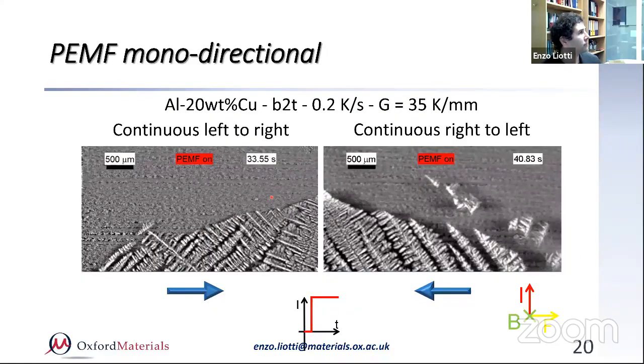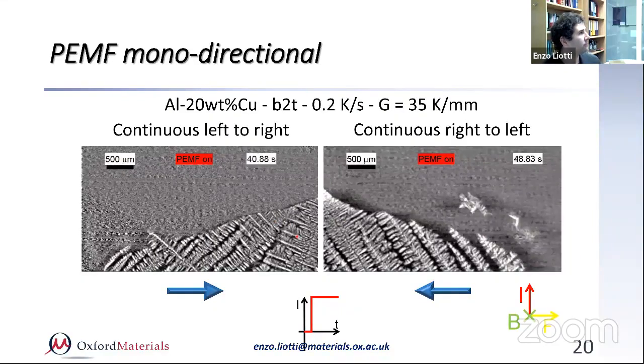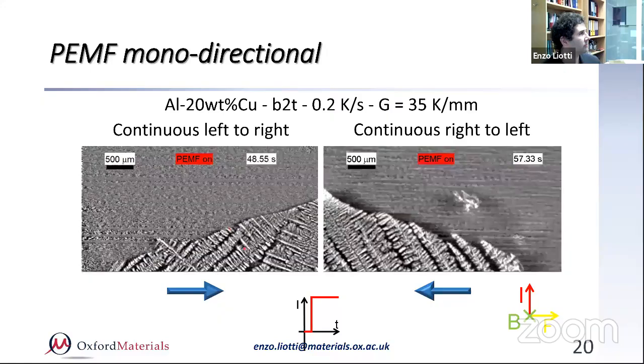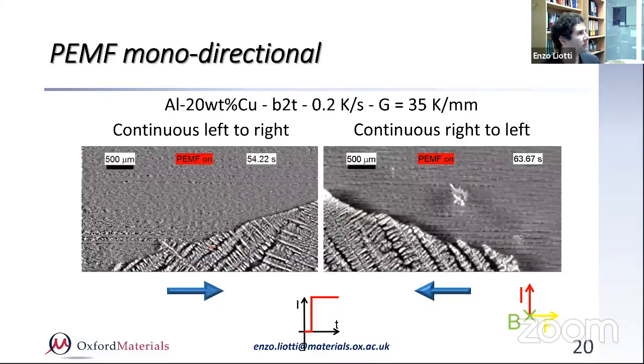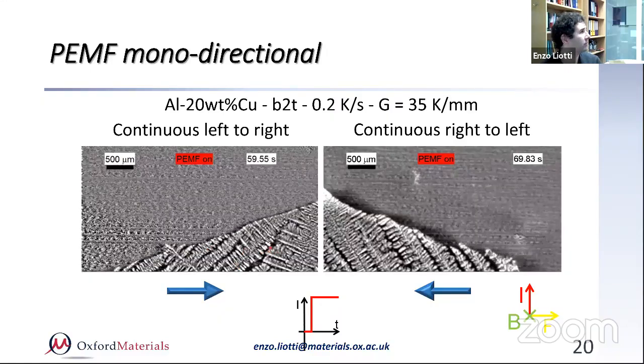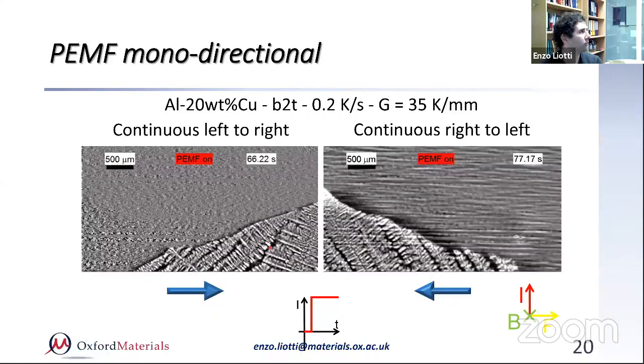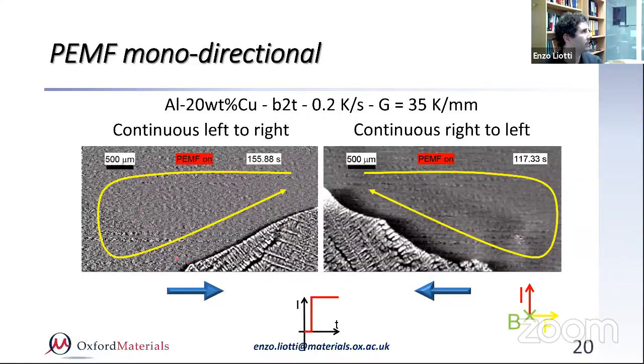The interesting thing is that you are remelting the top, but if you look carefully inside the mushy zone, not much happens. So this condition, in essence, doesn't really lead to fragmentation. It just leads to a kind of steady state flow that makes the liquid recirculate and remelt the material.